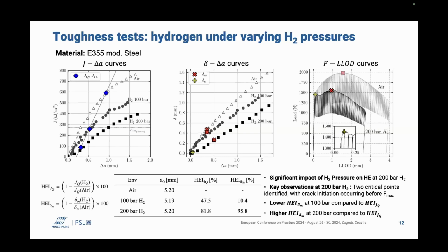We can see also the results for CTOD. That is interesting because at 200 bar we have what we can call a popping, just at the beginning of the plot. And we consider this as the critical CTOD in this situation, which leads us to a very high hydrogen embrittlement at 200 bar.